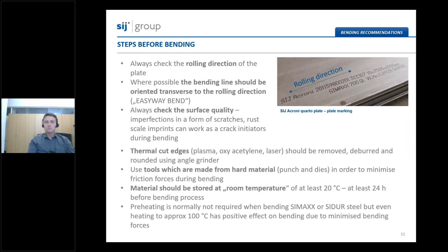The first step is to check the rolling direction. So the marking on our SIDUR and SIMAXX steel grades is always aligned along the longest edge. So this edge is also the rolling direction of the plate. And if possible, the bending should be positioned perpendicular to the rolling direction. Bending in this transverse direction is also called the easy way bend.